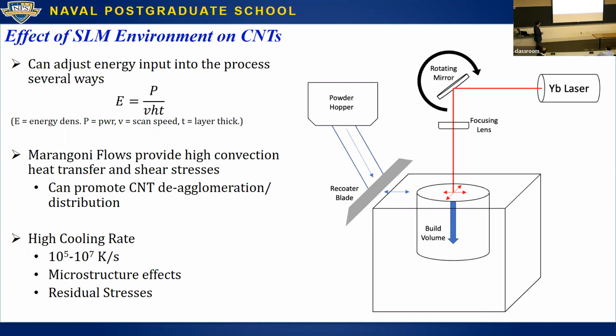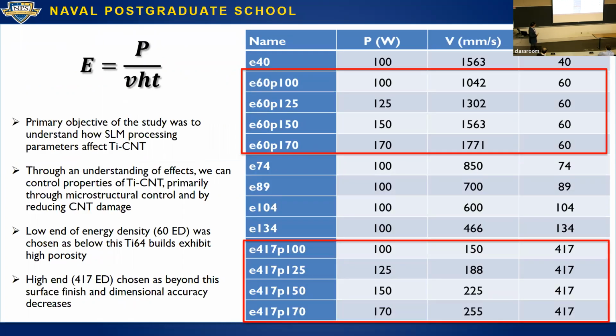In this first study, we're really interested in seeing how the presence of CNTs influences the effect of these variables, with the energy density being our primary interest. This nomenclature, E60, refers to the energy density, and the second number refers to the power. For example, we might get an energy density of 60, but we can use a range of powers and compensate with the velocity. If we're using a higher power, then we have to stay there for a shorter time, or move quicker. Our first work focused on a relatively low energy density of 60 and a higher one of 417. To give you an idea, the base energy density for Ti-64 that the company provides is 66.